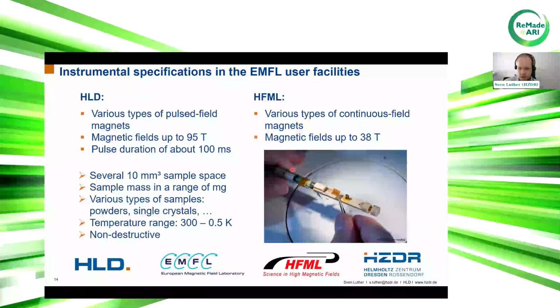And to show you, this is the picture of our sample environment, because from the bore of our magnets, we have a limited sample space. So this is a typical probe which we have, but these are always different for the different techniques, though more or less similar. You can see here we have several 10 cubic millimeters of sample space. And usually we have sample masses in the range of up to milligrams. We can measure on various types of samples, powders, single crystals, and more. We have a huge temperature range from room temperature or also above down to 500 millikelvin, and our measurements are non-destructive.